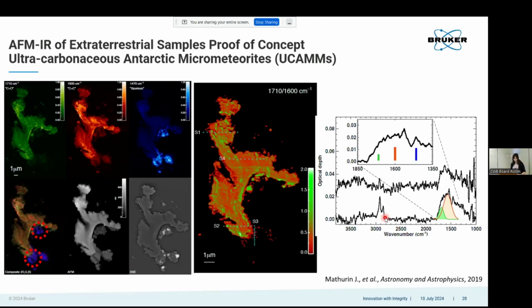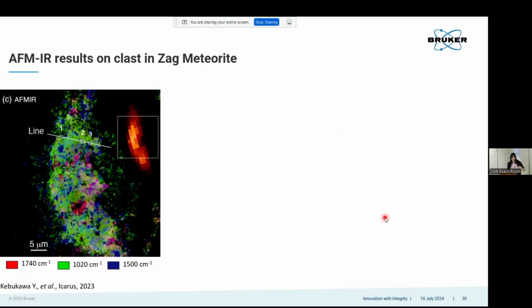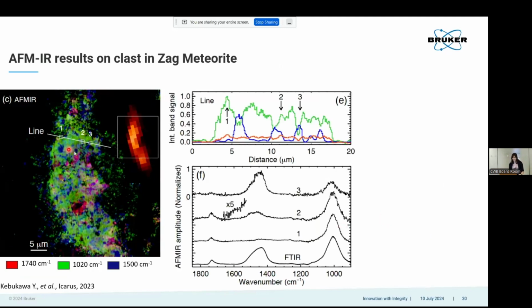PAHs. Okay, so then in a similar material, this is another ultra carbonaceous material, and they want to look at the spatial resolution of the technique. And so here they find this material. We're also, again, looking at these carbonates and at 1500 for the PAHs. And you can see that in this line across here, the variation in the three signals. So 1020 corresponds to the background. So what is the actual material that it's being transported in, which is a silicate meteorite.